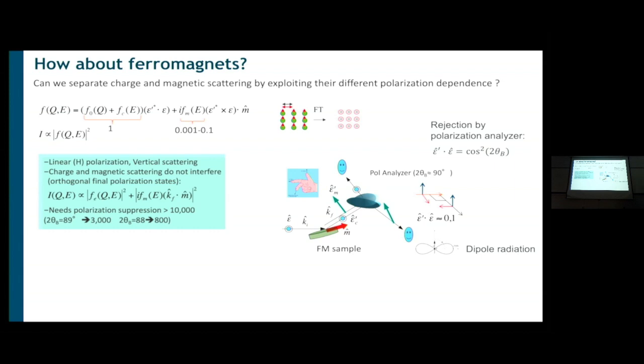Well, it turns out that it's not easy because to do polarization analysis, what we do is we leverage the properties of dipole radiation. In dipole radiation, if you look at radiation that is polarized in a certain direction, you see the most intensity looking perpendicular to the polarization. But if you look along the polarization direction, or in this case from here, you see nothing. There is no intensity there.